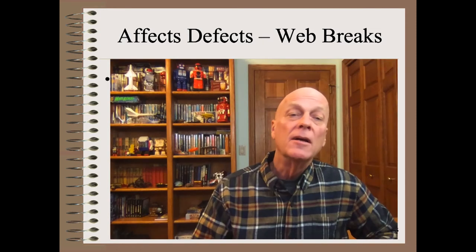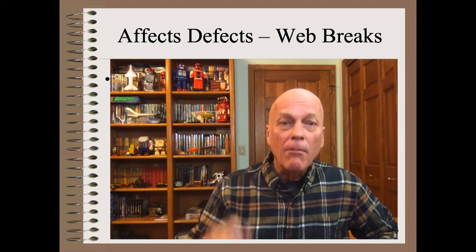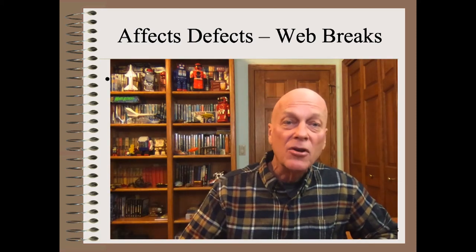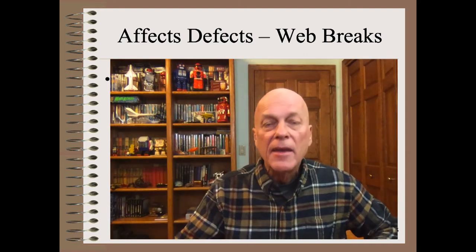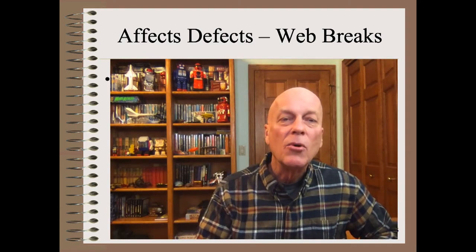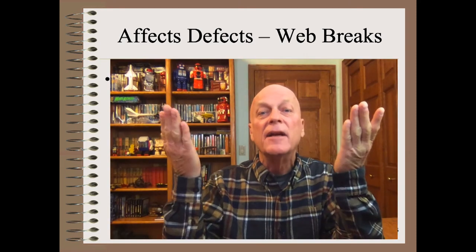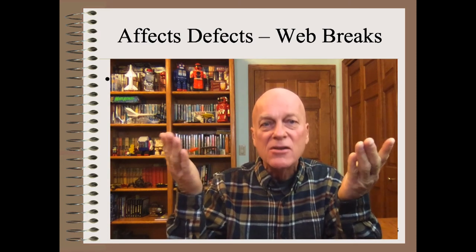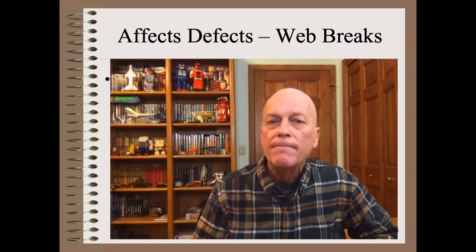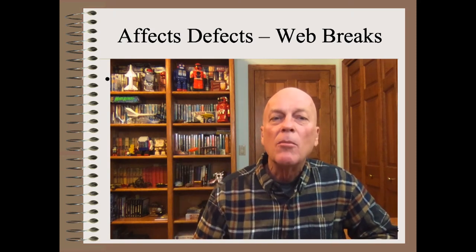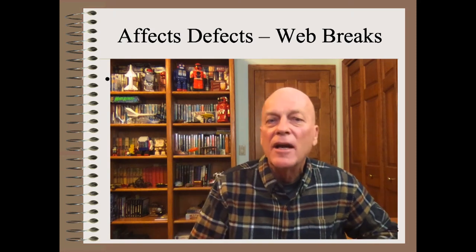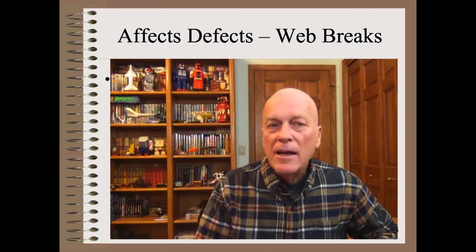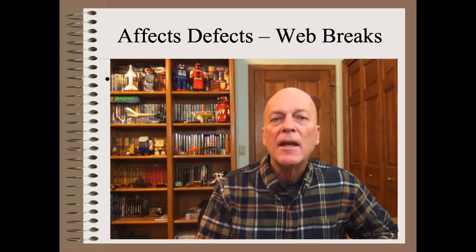Why? First, most web breaks start on the edges, so all you have to do is treat the edges. Second, increasing moisture there increases the toughness, which, as we saw, is more important than strength for runnability anyway. Third, increasing moisture takes the tension off the edges — think of it as minor, mini baggy edges.